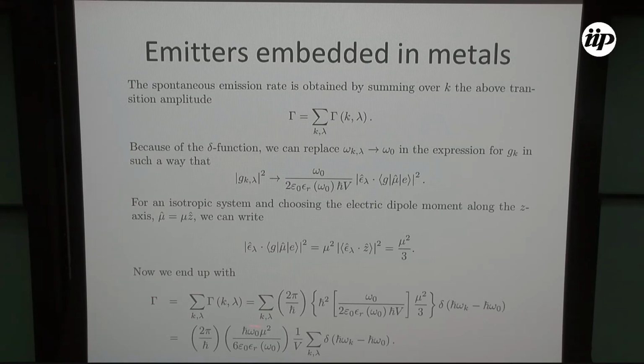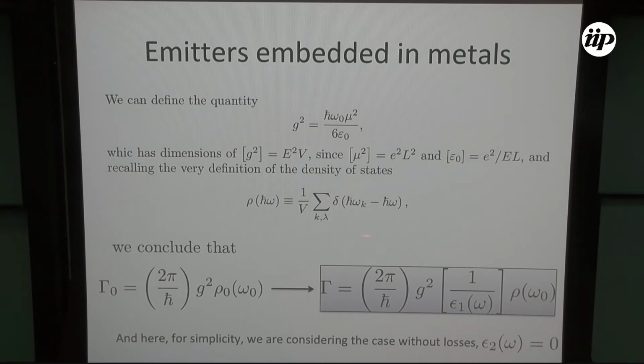So if I do the summation, the last line is the interesting one. Again, I obtain something which is 2 pi divided by h bar, something squared, and this is simply the definition of the electromagnetic density of states in the medium. So with this definition, and I just defined this coupling constant g squared, we conclude that simply by placing the emitter in a metal, I go from the vacuum result to this other result here. 2 pi over h bar is the same, g squared is the same, but I get two things here. I get 1 over the real part of the dielectric function, and the density of states doesn't carry this 0 anymore. It's the density of states inside the medium.